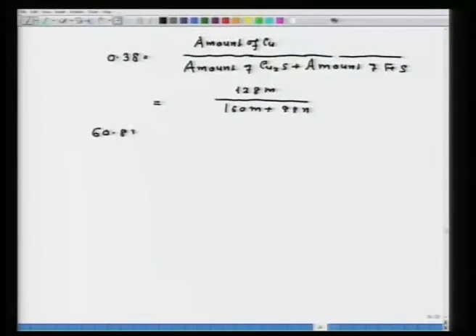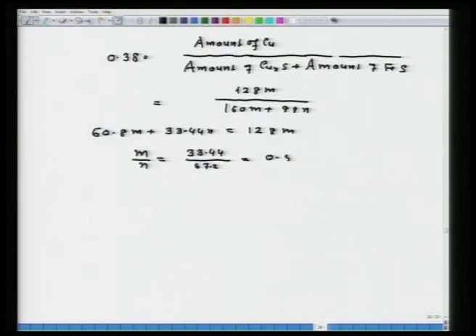Here again, the molecular weights, atomic weights, everything I have given. So, all that you have to solve. If you solve this equation, you will get, for example, 60.8 m plus 33.44 n equal to 128 m. Here you can calculate the ratio of m to n, equal to 33.44 upon 67.2, which is 0.5. That means you have the composition Cu2S·2FeS. So, that is the composition of the matte. However, in the ratio of m to n, say for example 2 Cu2S 4 FeS or 4 Cu2S 8 FeS, whatever the composition, in all the composition range where the ratio of m by n is 0.5, the grade of the matte will be 0.38.